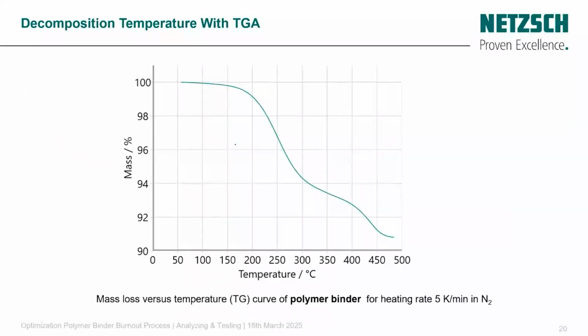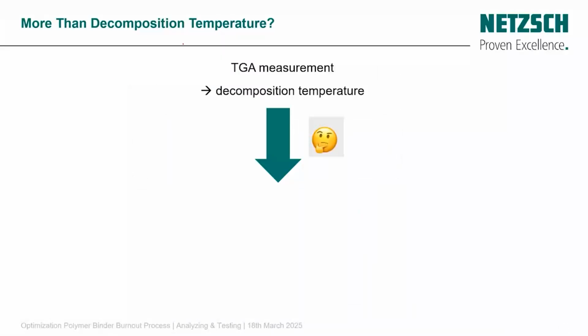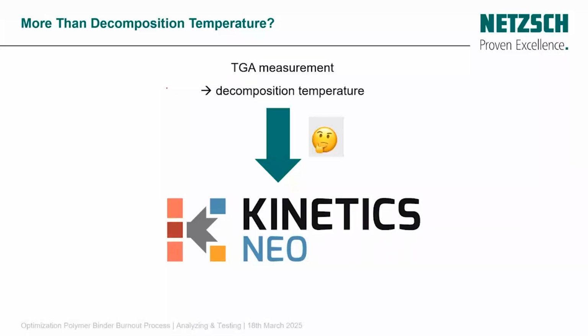So the first step is that we do the measurement by the TGA. We can see here the mass loss versus temperature curve of the polymer binder for a heating rate of 5 K per minute under nitrogen atmosphere. And this curve can give us an idea about the thermal stability and also the decomposition temperature ranges. So what can we do more than only determine the thermal stability and the decomposition temperature? Now we have Kinetics Neo, which can help us get the kinetics parameters to do the prediction and also the process optimization.